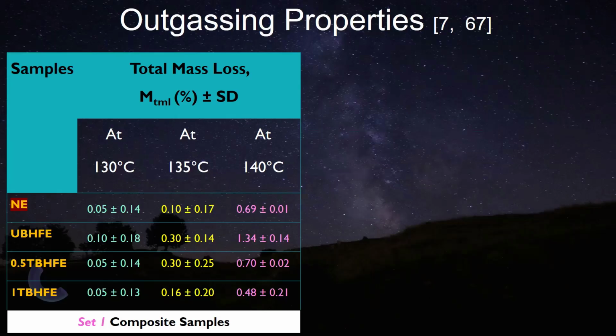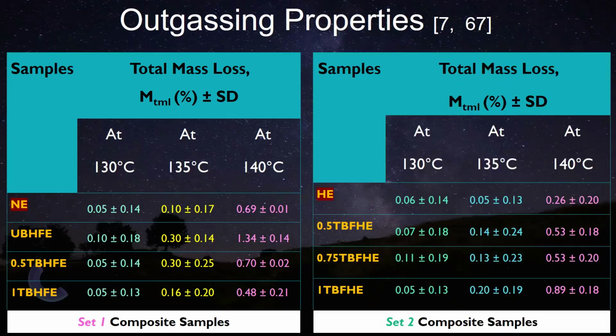One is static and dynamic. That's the article, actually, number 7 article. You can investigate that further. So that's why I added three different temperature conditions: 130 degrees, 135 degrees, and 140 degrees. And that is for both actually. And we found that although we have the equipment limitation, that value is below our set value.